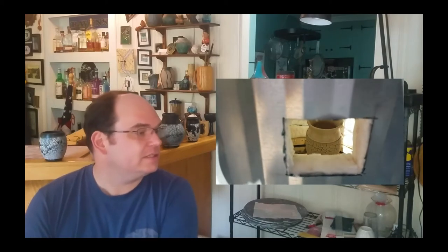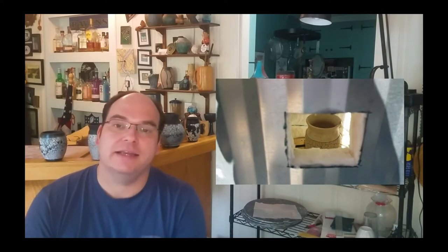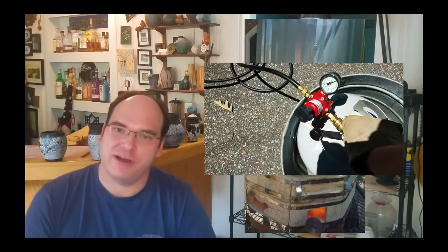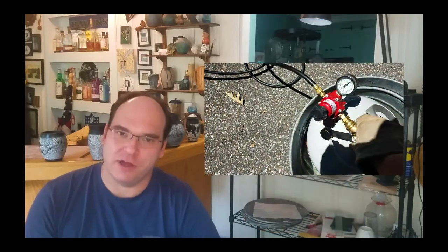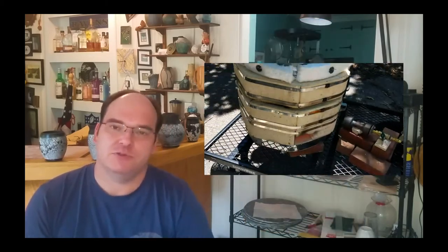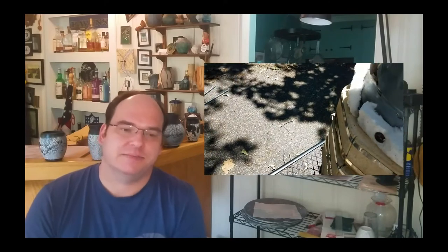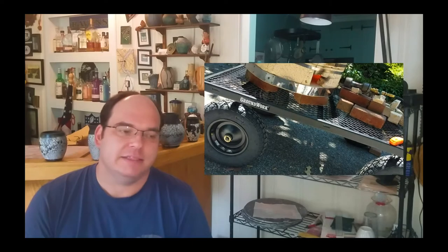So once the slip is dried and cracked and is the patterning you like, now it's time to actually fire. We fire our kiln in steps. We like to feather our fire with five minutes on and one minute off. And you can reach your optimal temperature for this particular process, about 1500 degrees, in 10 minutes. So we do five on, one off, five on. And then we use a visual process just to make sure in the last couple minutes that we're at the temperature that we want to be at, at the spot that we want to be at.